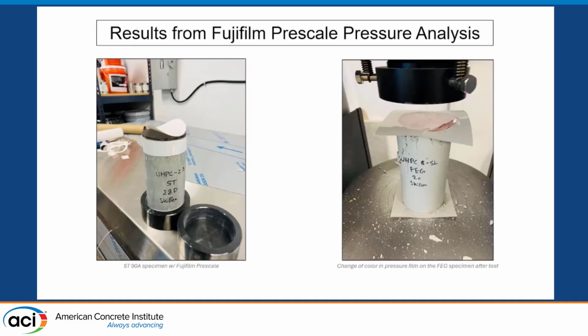And what I said earlier is we wanted to characterize the end conditions and see how the concrete was interacting with the pad. And so we did this by using these Fuji films out of recommendation from Pratik Shah from Wiss, Janney, Elstner. We did this for when a UHPC cylinder was getting tested with pads. We had the steel cap, we had a film in between the steel pad to measure that interaction, and we had a film in between the pad and the concrete surface interaction.